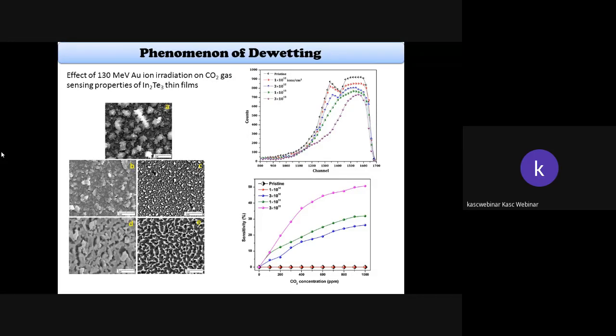Again, our group also studied the phenomenon of dewetting by using an indium telluride sample, which is subjected to a 130 MeV gold ion irradiation. Especially this is very helpful to fabricate carbon dioxide gas sensing. The first diagram clearly indicates the pristine sample A, which contains a surface indium layer deposited over a tellurium sample, and if it is subjected to lower ion irradiation, like 1 into 10 to the power of 12 ions per centimeter squared in a particular period of time, it melts the surface layer.